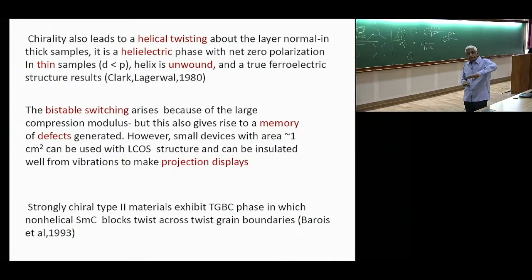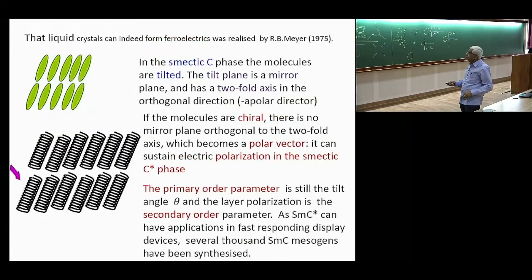And this can be switched from one to the other. Let me go back to this. You see, if the polarization is looking towards you, and the molecules are tilted that way, if I apply the opposite electric field, the polarization should look into the board, and then, therefore, they have to tilt the other way. So there is a clear change in the orientation of the tilt, and therefore this can be used in an electro-optic device, like a display. And they showed that this change can be brought about.